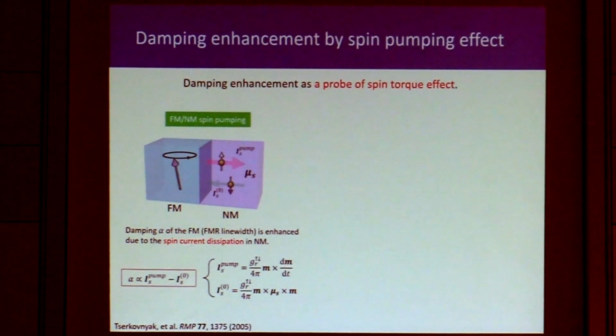So what we do to characterize the spin dissipation in the antiferromagnet is use the spin pumping effect. It's a very famous effect where a spin precessing magnetization can pump a spin current into the adjacent non-magnetic material. Depending on the spin dissipation property in the non-magnetic material, this pumped spin current creates a spin accumulation, and it again creates a backflow current. Depending on the difference between the spin pumping current and the backflow current, it will give a damping enhancement. So by looking at this damping enhancement, we can characterize the spin dissipation property in the non-magnetic material.